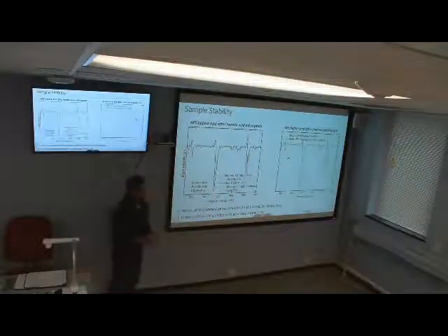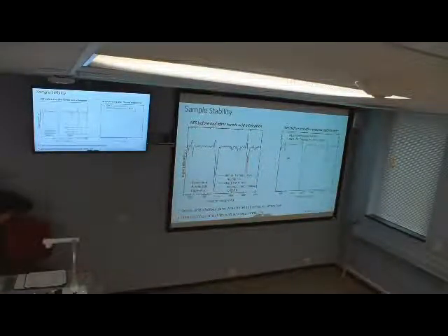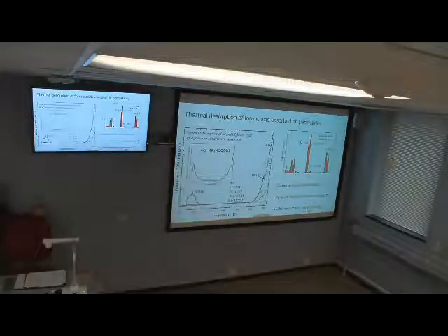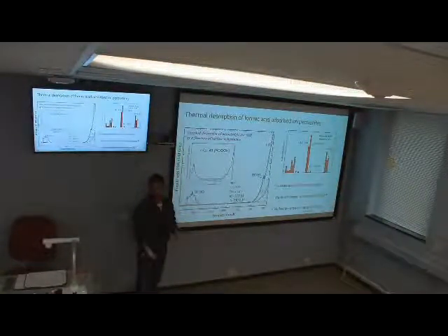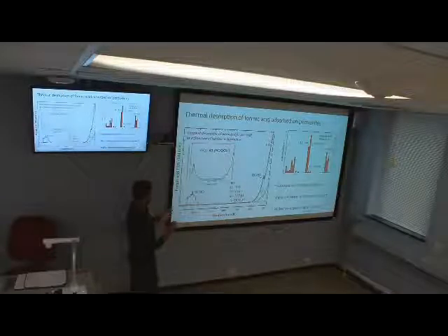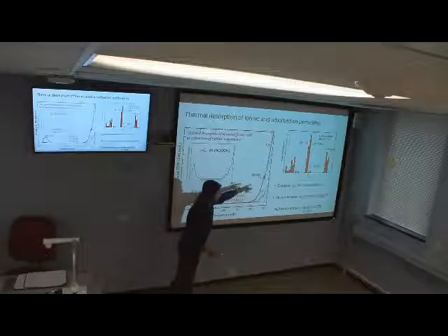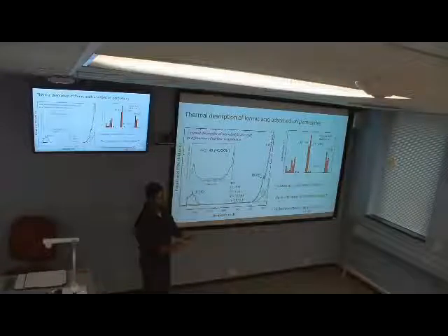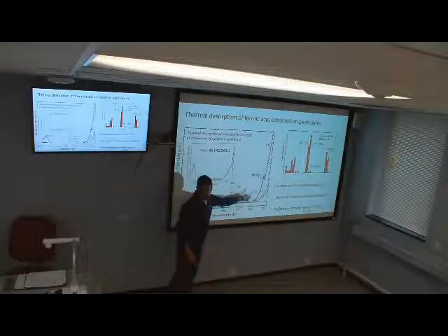I still don't have that here now. We did TDS like so. This is the first trial of formic acid dosing: we dosed formic acid into the chamber, ran the sample temperature and detected those fragments. After that we have somewhat dissociated formic acid structure, not completely, and we dosed formic acid again. And we had a similar kind of TDS peak pattern.